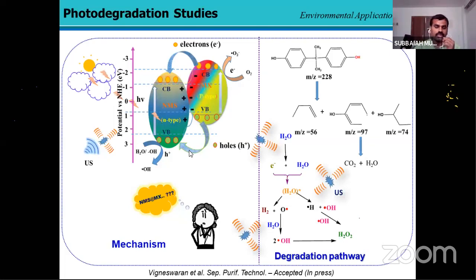We have also tried to degrade rhodamine B as well as phenol. Both work well on MXene-based material compared with the graphene-based material, with higher efficiency and a lower rate of adsorption capacity loss than the other 2D materials as well.